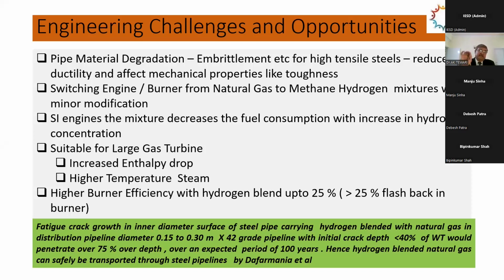And one good study, because the embrittlement leads to crack formation in the pipeline. That is a major challenge for any pipeline operator. One simulation study, based on the cyclic loading pattern, was carried out in the lab for a pipeline of X42 grade, because higher grade pipelines are more susceptible to cracking. It was done assuming less than 40% crack was already created in the pipeline, to see what the hydrogen environment effect would be.